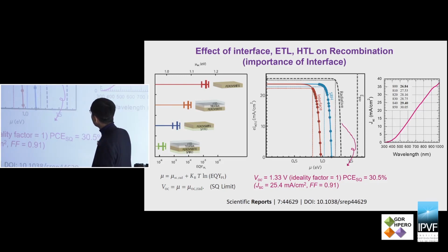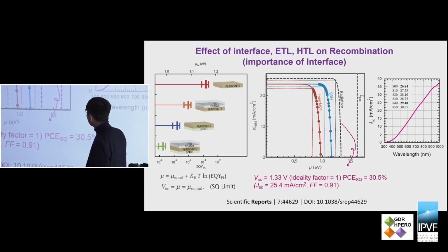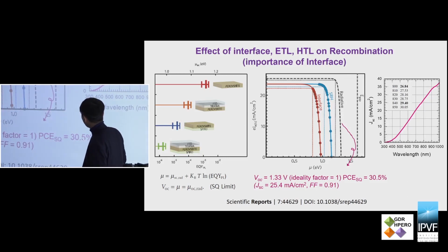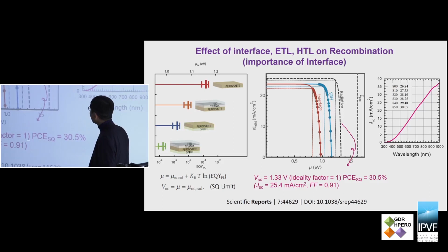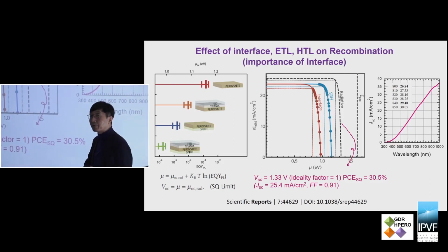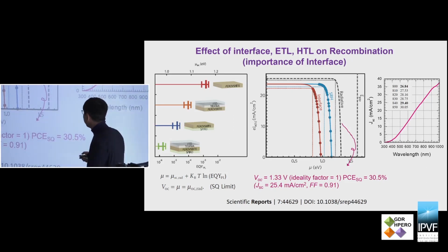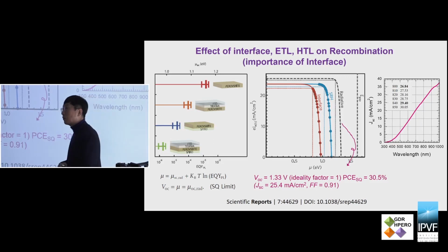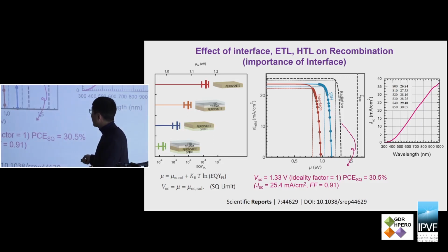So here is the calculation. If you allow only radiative recombination, meaning you don't have any defects in the perovskite film and no interfacial recombination, then 30.5% efficiency can be expected, because the open circuit voltage is around 1.33 volt. Now we have 1.16, less than 1.2 volt, in real systems, and the fill factor could be 0.9, while the best fill factor now is 0.85. So if you work on reducing the recombination, we can get this kind of open circuit voltage and fill factor.